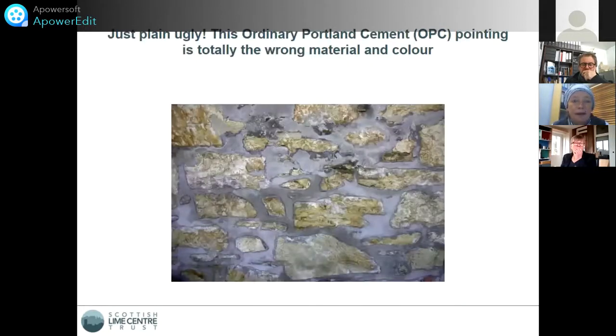And here's just the plain ugly, totally the wrong material, and actually if the person doing this work had read the wall properly, they would have seen remnants of original lime harling and lime wash on the faces of stones, and that's been completely ignored. And I suspect this uses the cement from the Dunbar cement works, Blue Circle works, where the colour of the cement has got darker and darker over the last sort of 10 to 15 years. It's almost sort of navy blue grey colour, so not matching at all.